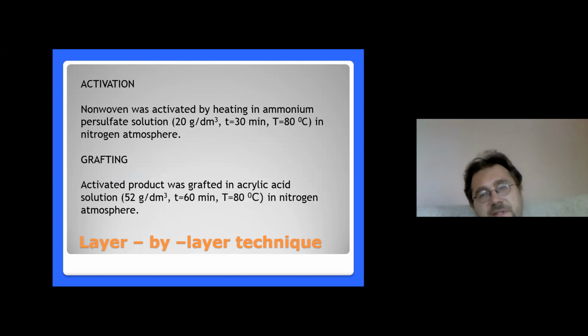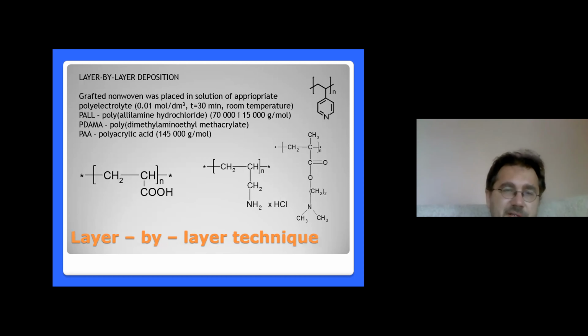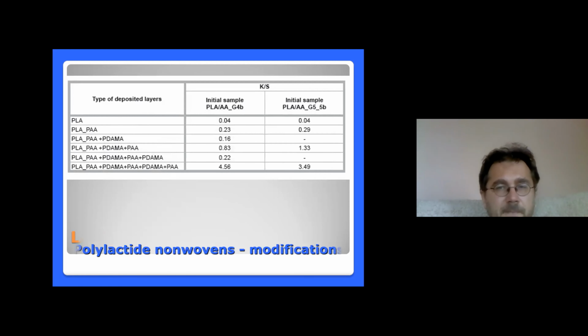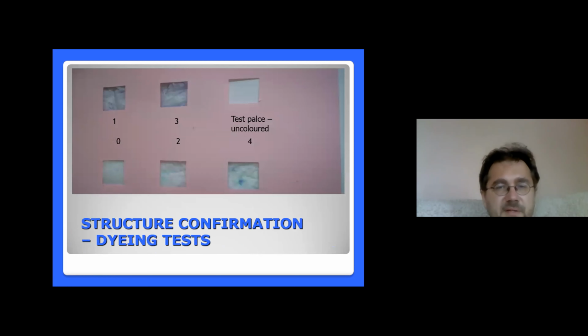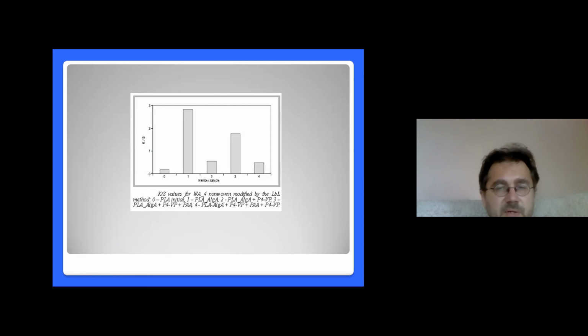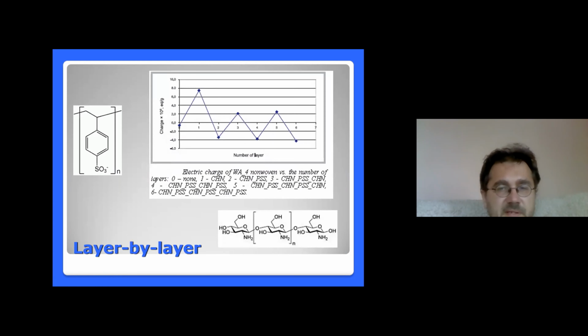The advantage of this methodology is that it's also quite easy, but not as easy as padding. But we don't need very harsh solutions, because the layer-by-layer deposition is at room temperature, and the concentrations must be very low. Time is short, and we use water as a solvent. So in this way, we introduce polyacrylic acid, polyallylamine, and different polyamines. We introduce here 4 polymers as an external layer, and we confirm the structure by using coloring tests. Here, we controlled this color. Let's see examples.